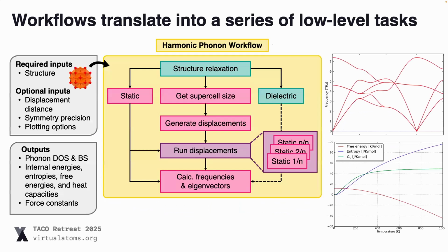So we have over 100 workflows. Each one of these is essentially a mapping from a very high-level description to a series of low-level tasks. And so this is an example of the harmonic phonon workflow. Many of you will have done this by hand. And so essentially we take a structure, we relax it, we create a supercell, and in fact, technically we do increase supercell size to kind of check for convergence. We calculate the dielectric constant so we can get the LOTO splitting, and we run a series of displacements. And you can see all the user has to do is submit a structure and say, run this one workflow, and under the hood, all of these different steps will be done, and then we can pull out the heat capacity and phonon band structure and things like that at the end.